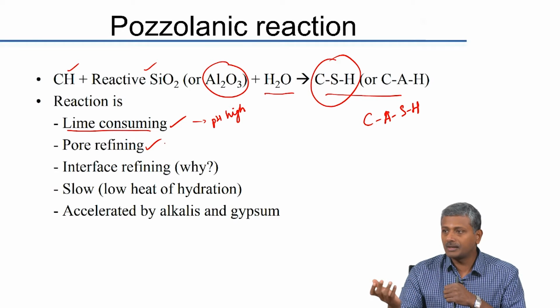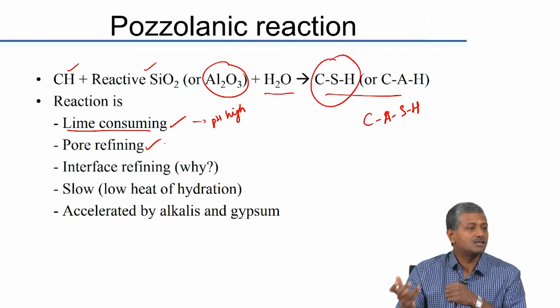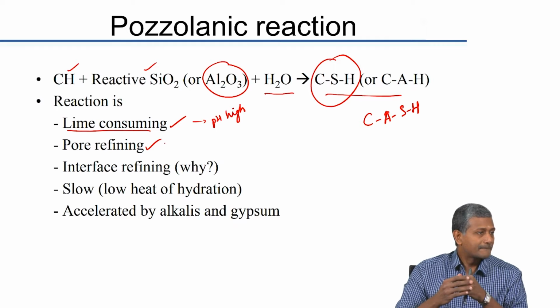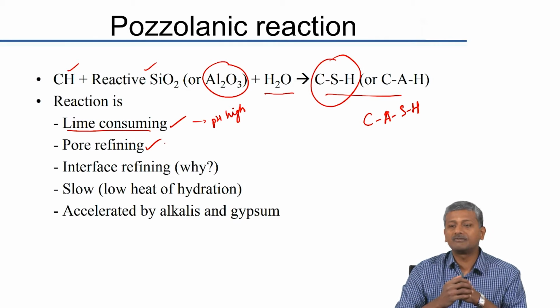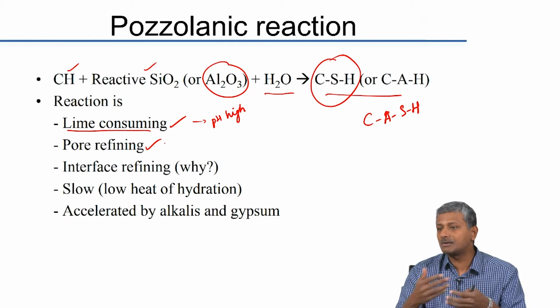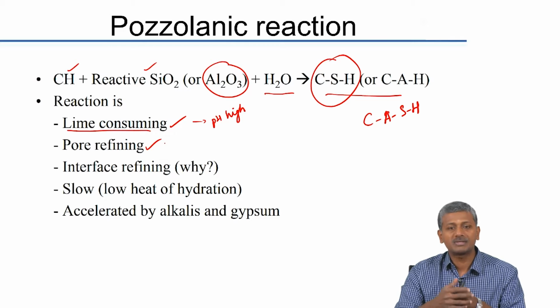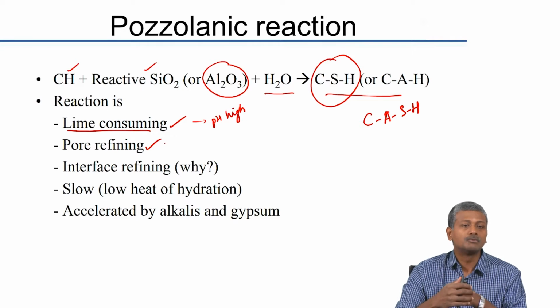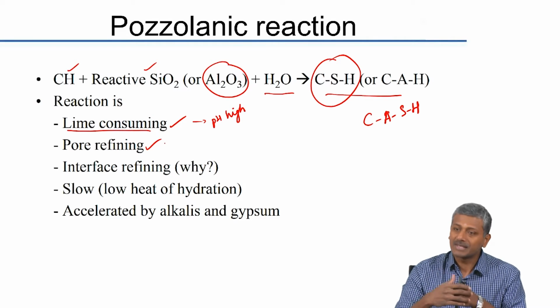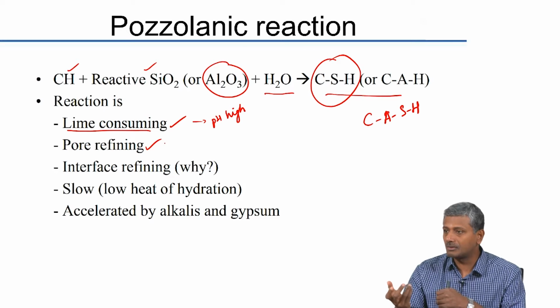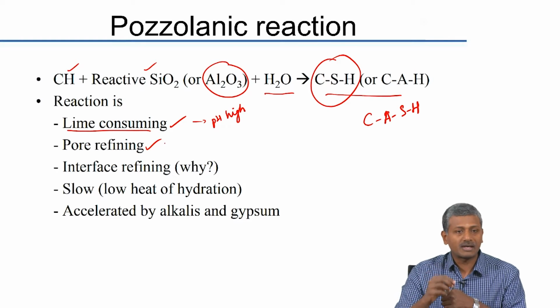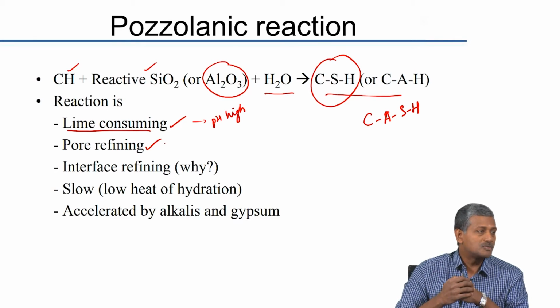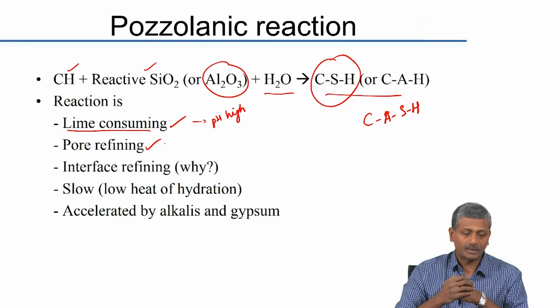Again, why does that happen? Why does the interface get refined? There is more calcium hydroxide found in the interfacial zones. So, obviously greater conversion of calcium hydroxide to CSH happens at the interface, which leads to an improved performance of the interface. Secondly, there is also the filler effect of the mineral additives. So, the fillers can actually go and block the open spaces available close to the interface, right.